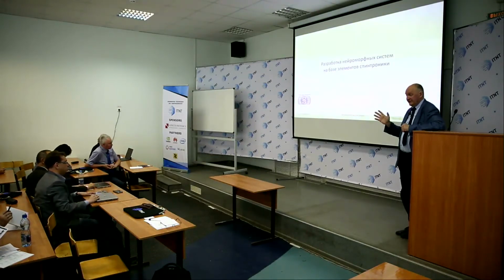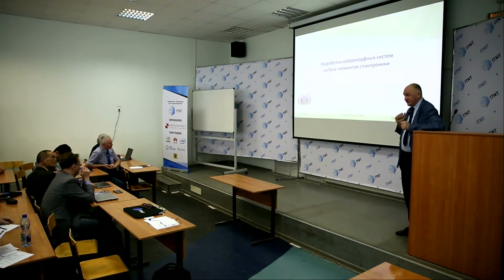Antiferromagnetic materials, because magnetization is almost zero there, are absolutely not affected by big changes of temperature. The temperature should just be lower than the Néel temperature, where the antiferromagnetic order changes. And for many materials, like hematite, this Néel temperature is a few hundred degrees centigrade. Therefore, they are very stable to temperature change. They are also very radiation-stable, much better than semiconductor materials, because there are no electron carriers there at all. They are not used as carriers of information. So in some applications, they are much more applicable than semiconductor materials.